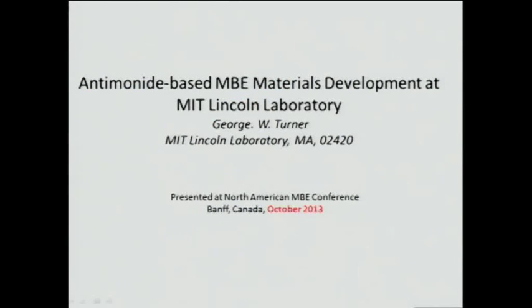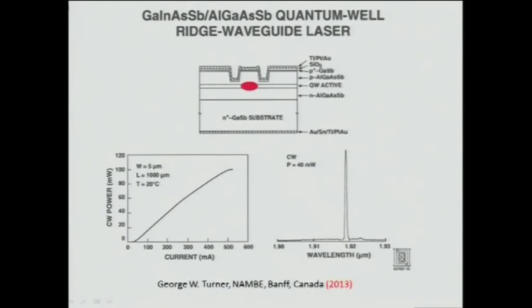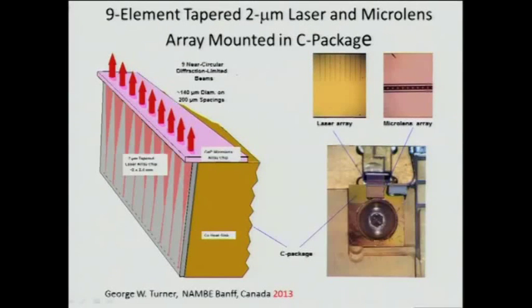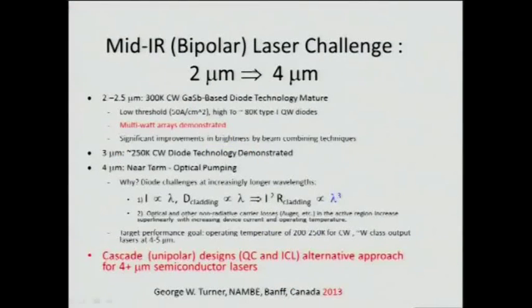I also want to mention another very nice development, the growth of antimonide material by George Turner from the Lincoln Laboratories, also at the same conference. He grew indium gallium arsenide antimonide, aluminum gallium arsenide antimonide quantum well ridge waveguide lasers, lasing in the 2 micron range. Also, he mounted a 9-element tapered 2 micron laser with a microlens array in the C package to have a multi-watt output for these 2 micron lasers.